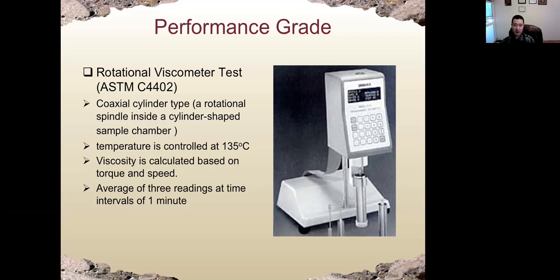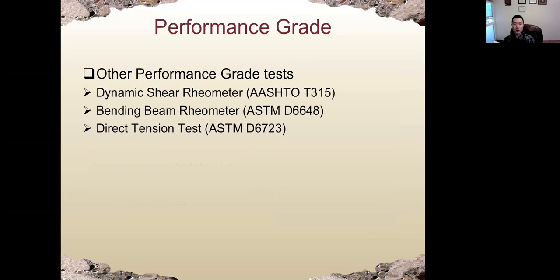Again, the temperature is well controlled at 135 degrees Celsius. And we can calculate the viscosity of asphalt based on the torque and also the speed of the spindle. Okay, so this is a very commonly used viscometer. We can use this for asphalt, and we have also used it for Portland cement paste. Okay. Other performance grade tests, including shear, bending, or tension tests, are for the mechanical properties of asphalt. All of them are ASTM or AASHTO standard tests. Okay. We just skip the details of these tests.